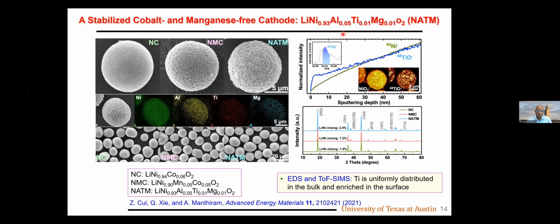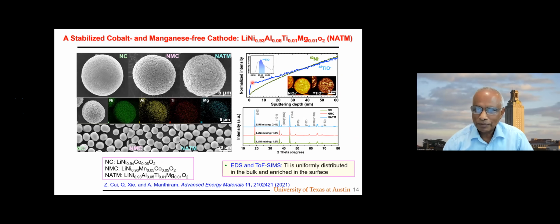So now I'm presenting here a composition without any cobalt, without any manganese, and that is NATM with 5% aluminum, 1% titanium, and 1% magnesium. That is compared with 2 other materials. The compositions are given here, and all of them have around 90% nickel and nice X-ray diffraction patterns. Only in the case of NATM, we see the titanium a little bit on the surface. It is also in the bulk, but a little bit more enrichment on the surface, as indicated by time-of-flight secondary ion mass spectrometry and EDS analysis. And they all have similar particle size, as you see here.